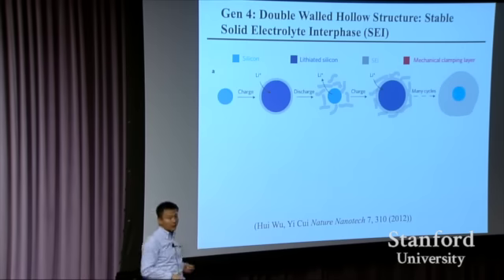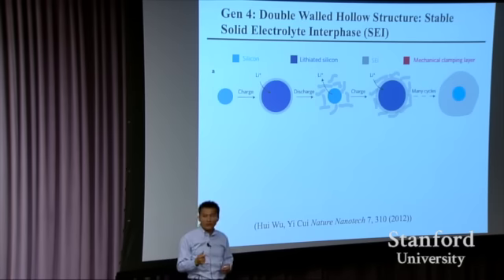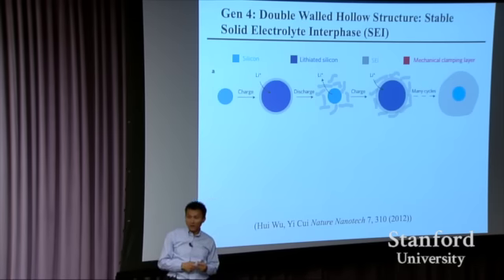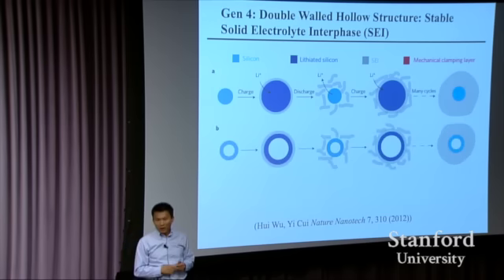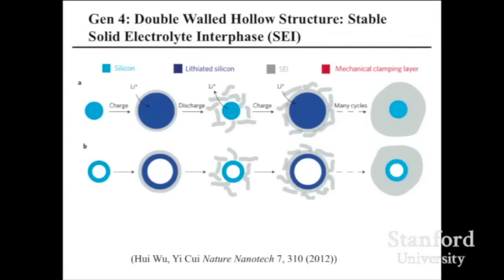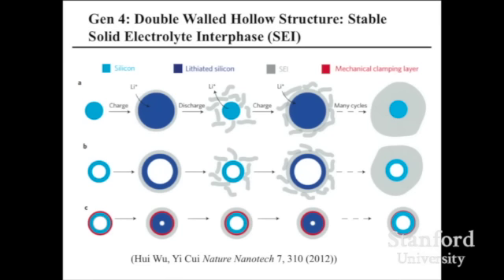Later, this becomes too thick. These layers consume your electrolyte and consume your lithium. Batteries die very fast, even with nanostructures. Hollow structures go through the same expansion and contraction process. Batteries also die, as you consume electrolyte. So this became a really tough problem for several years, until one day we came up with this idea. What if I make a hollow structure, and on the surface, I put this red color coating, mechanically very, very strong? Lithium can still come in to react with silicon, the blue color.